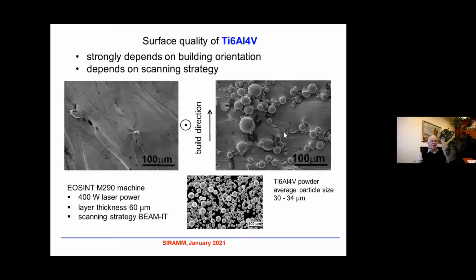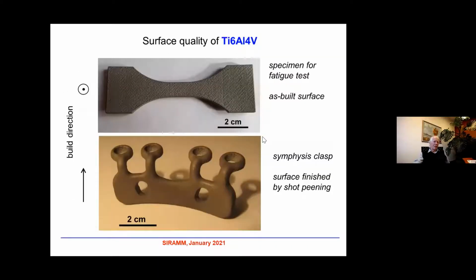On the right-hand side, you can see the lateral surface. This is the build direction here. And we can see that there are not fully melted particles attached to the surface. So the surface is strongly dependent on the orientation. An example of a specimen for fatigue tests, which was built with an as-built surface, is shown here. You can see here the traces of the last layer, of this strategy.